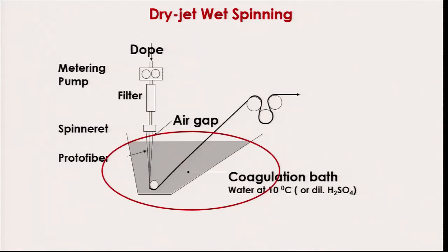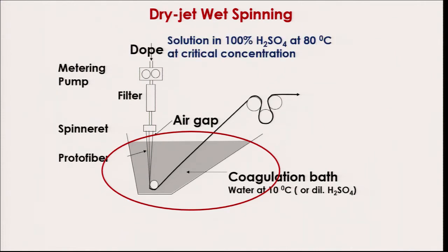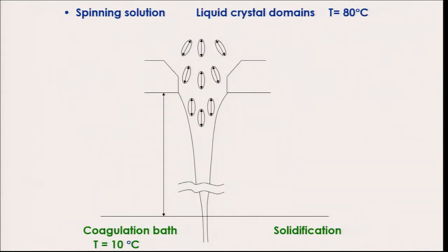If I look at the process of spinning, the dry jet spinning method, in which the spinneret is in the air, it is not immersed in the coagulation bath, right. The coagulation bath is below the spinneret, the fiber is spinning in the air gap, the dope is in 100% sulfuric acid at critical concentration, higher than critical concentration, and after the spinning the washing is being carried out using NaOH. If I see how does this structure result in very high performance properties.